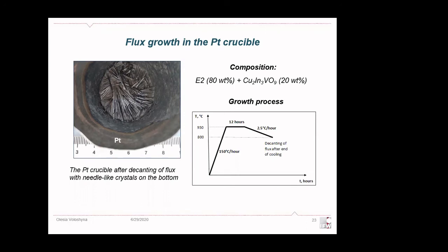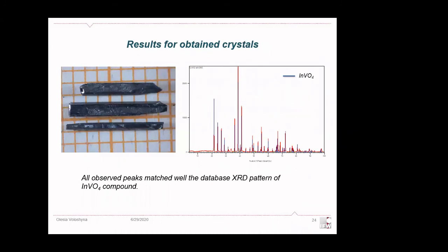So we used the platinum crucible, again the same composition, but the only change in this experiment was that after slow cooling to the temperature of 800 degrees, we just switched off the furnace and then just decanted the flux at room temperature, but the mixture was still hot. And we obtained the crystal, good faceted, just slightly decorated with a flux. And XRD analysis proved that this was pure indium vanadate.